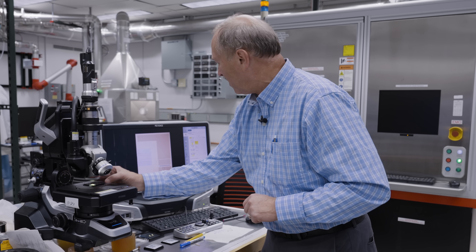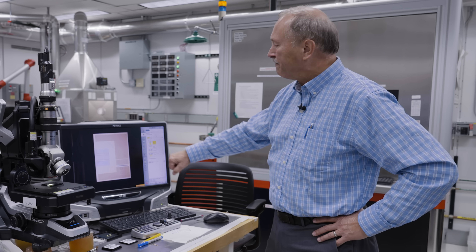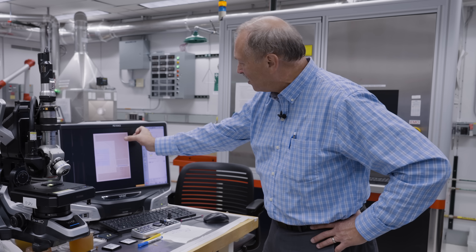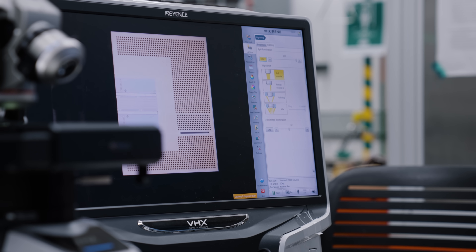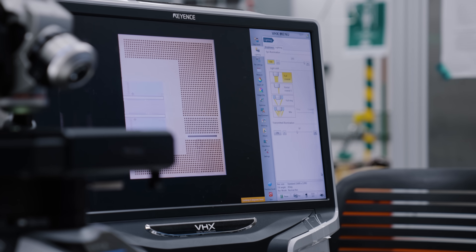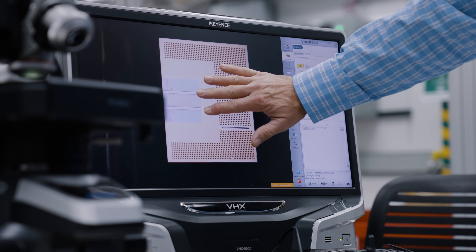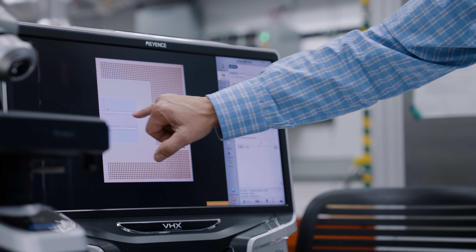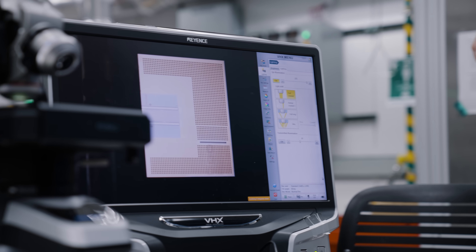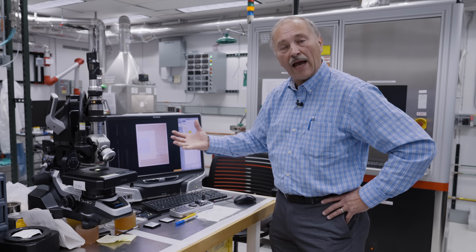When I put it under the microscope, you can see on the screen what the chip looks like. This is one of the two test vehicle chips that we designed. On it, you'll see an area that looks a little bit orange. That is an array of solder bumps, and those solder bumps allow us to have electrical connections on and off the chip. We've also got an area where the polymer adhesive and polymer waveguide will attach. Within that area on the chip there are optical waveguides that run parallel to two bars, carrying the light to or from the chip to allow that communication link.